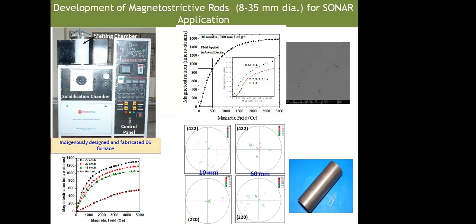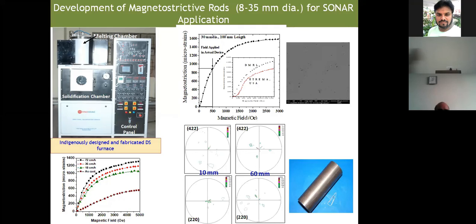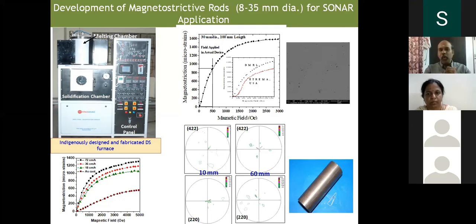For scaling up, the zoning technique was not a viable technique for us because the sizes we require are not suitable, and further the magnetostriction we achieved was also relatively low. And there is a huge reaction between the metal and the mold. There are some other challenges as well. So we have gone for indigenously making our own furnace, and this is the Indivac fabricator. The Indian company Indivac has fabricated this, and this is a modified Bridgman furnace.